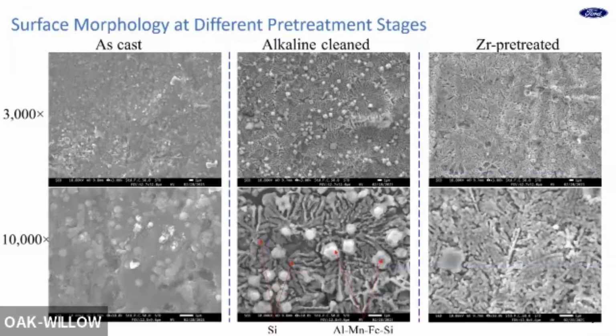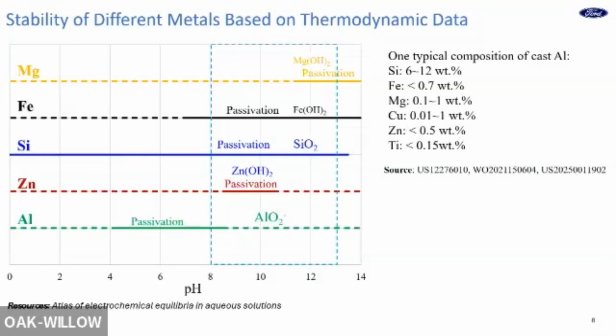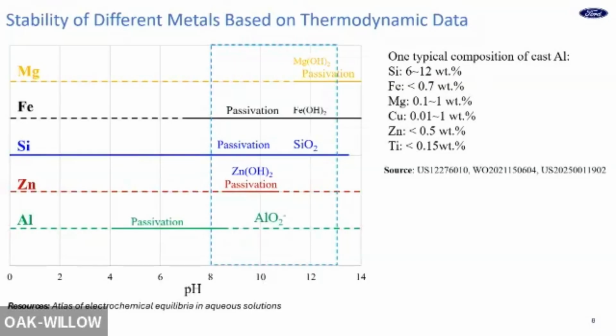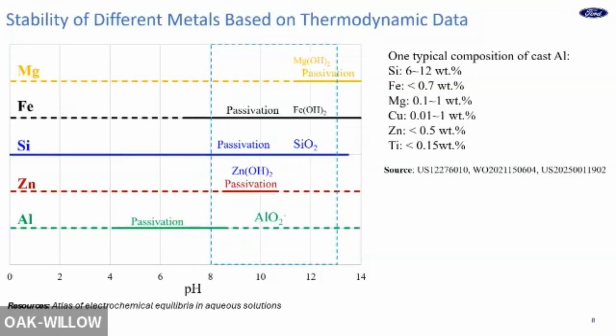So you can see, in the alkaline cleaning solution, the pH is normally high, so aluminum can corrode and form aluminate. But silicon can form a passivation layer, silicon oxide, so it can protect against dissolution. So if you imagine you dip the cast aluminum, which has a high amount of silicon, in the high pH alkaline cleaning solution, aluminum will dissolve, but silicon will passivate on the surface. So this is solely based on the